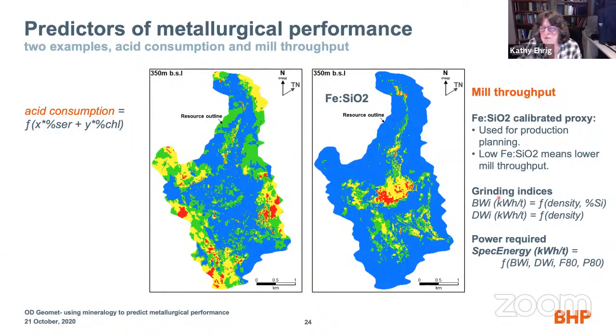But believe me, we also do the proper testing from that, and there are the classic grinding indices that we worry about, bond work index and drop weight index, which are important for metallurgists and the designing of process plants. But actually, these indices can also be described as functions of simple things like the density and the silica content in the ore body. Then we go further. The amount of power that we're going to consume in that mill is a function of these grinding indices and the feed size of the material going into the mill and the size of the material that we grind it down to.